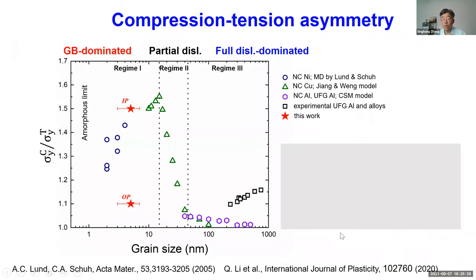All right, so then if you compare the data to literature data to put this into perspective, this is a chart that Chris Schuh did years ago, looking at the yield strength, sigma_yc, yield strength in compression, and sigma_yt, yield strength under tension. Look at the ratio versus grain size, and you see this interesting trend. When grain size is pretty large, more than about 100 nanometers, this ratio is close to one, meaning tension and compression are symmetrical. In many cases, this is the regime where the material is relatively ductile. These are data coming from nickel, copper, and aluminum.